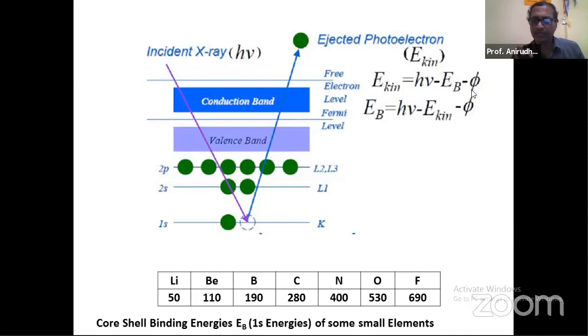See, h nu is the energy of the X-ray which emanates from the source and which falls on the surface. So you know at what frequency that is happening. So that h nu parameter becomes known to you. Now, if there is some method of getting the kinetic energy of that ejected electron, then we have become successful in finding out the EB, the binding energy. So there are sensors or detectors fitted inside our equipment, which can measure the kinetic energy of those electrons which are ejected in this process.